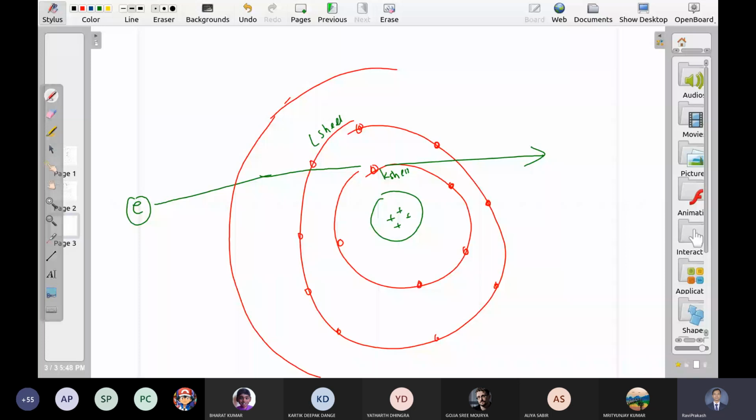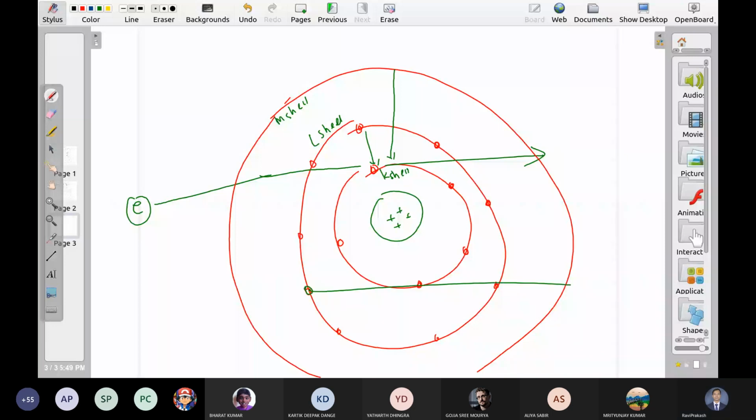Okay. So an electron can come from any shell, like L or M, or let us say an electron kicks out any electron from the L shell. Then an electron from M will jump to fill this gap, and in this gap this orbital electron will lose its energy. Why? The K shell has the lowest energy, E1. The L shell has somewhat higher energy, E2.